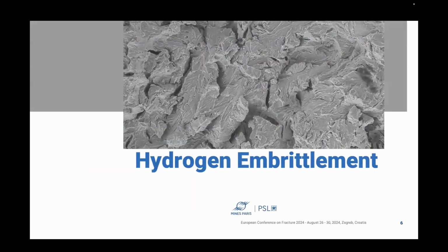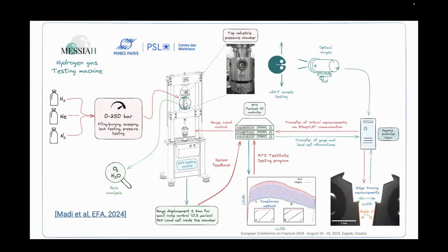Now to talk about hydrogen embrittlement. Here I have to spend a little bit of time. So this is our test setup for mini specimens in gaseous hydrogen. The heart of this test setup is the pressure chamber, a pressure chamber with 4 sapphire windows, and we can use these windows to put cameras and lights to do the edge tracing technique during the test pressurized with hydrogen. And we can follow what we want here. Here I show one example with a mini toughness test where I can follow the load line opening displacement and also the angle displacement.